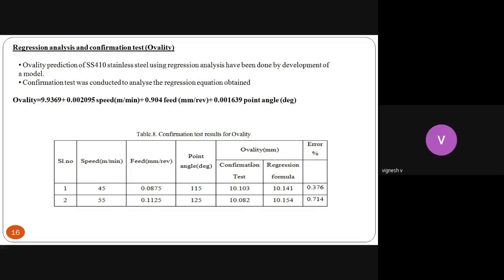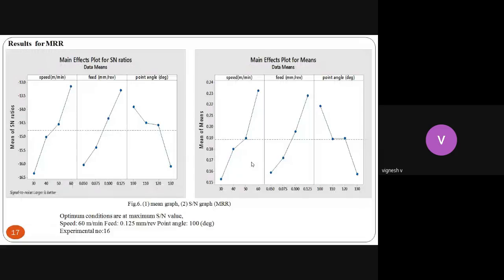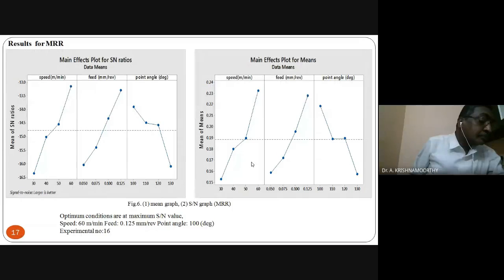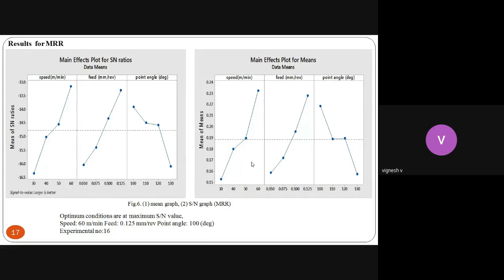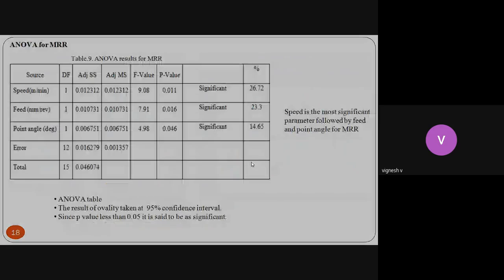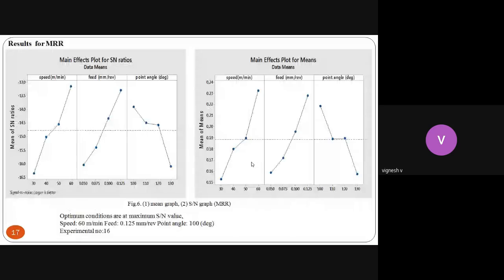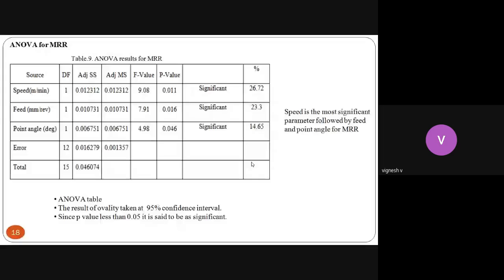Then in the case of MRR, which is another output response, we again followed the same procedures, and we get a maximum optimized value, and also we are able to identify the parameter strength. We identified that experimental number 16 is the maximum optimized condition for that set of experiments. And we can also identify that in MRR the speed is the most significant parameter, followed by the feed and the point angle.